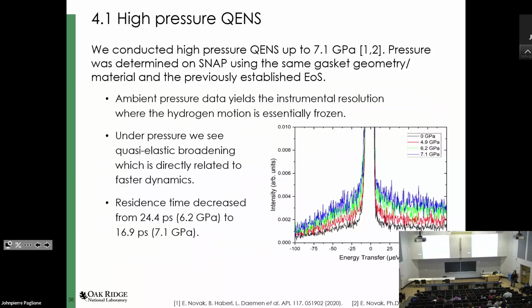So then once we understood how our particular sample in these large volumes behaves under pressure, we replicated this experiment on SNAP using the exact same gasket and the exact same geometry to again measure the pressure load curve for the specific setup that would go then on the QENS beamline. And then afterwards, we replicated the experiment on the basis instrument where you cannot get the pressure, but of course where you get the information you want to get.